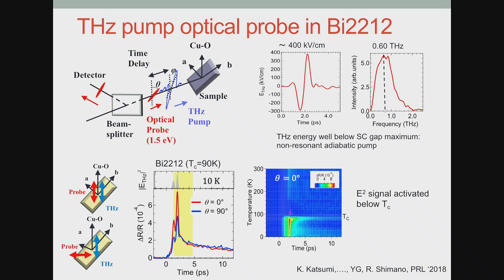One nice thing about using an optical probe in reflectivity configuration is that you can actually tune your light polarization. So you can quite easily look at the response as a function of the orientation of polarization with respect to the crystallographic axis. This is an experiment on bismuth 2212. So this is the change in reflectivity as a function of time. In red here, this is E squared of the terahertz pump. And what you see here in blue and red are the changes in optical reflectivity in two different polarization configurations. One where the probe electric field and the terahertz electric field are parallel, and the other where both are perpendicular. So essentially, I keep my terahertz electric field along the same direction, but I rotate my probe electric field by 90 degrees. What you see is that in both polarizations, you can see a signal.